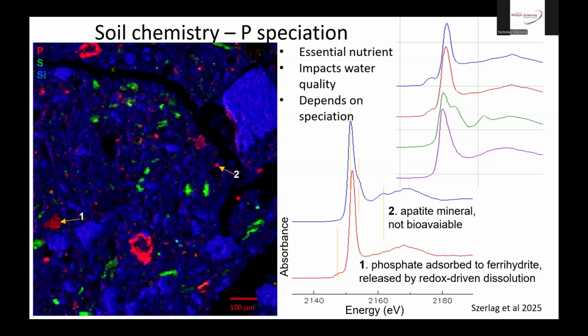Right. So the fluorescence emission lines, they may change very slightly with chemistry, but not within the resolution of the detectors used for this. You would have to use a much higher resolution detector. It does, and it's also chemical and structural. I believe that has been done for sulfur in a couple of special cases, using a high resolution detector. But typical fluorescence detectors don't have that resolution. But there's another approach we can use that I'll get to in a few minutes.